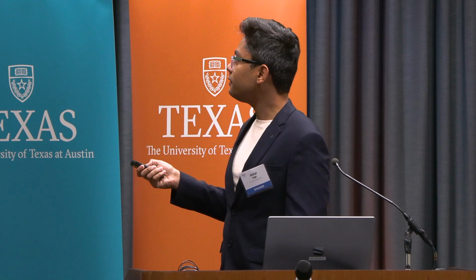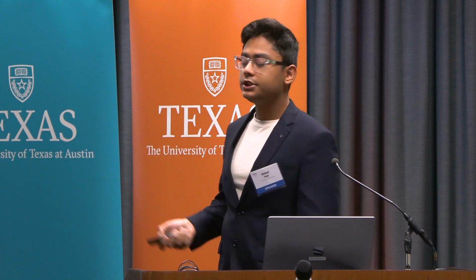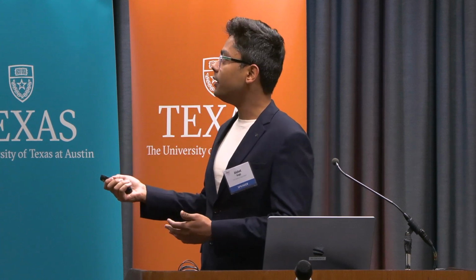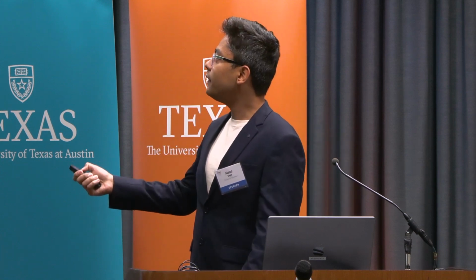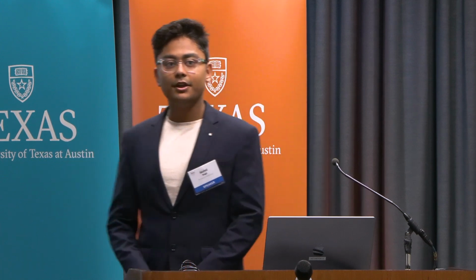So you can observe this phenomena with other metals and supports. One thing is that we want the support, which is TiO2 in our case, to be a reducible support. So it could be, let's say, niobium oxide, which is again reducible, but something like aluminum oxide cannot be used to observe this phenomena because it won't reduce even at high temperature. So that's one. And then you usually want the metal to be a high surface energy metal. So something like platinum, palladium, or even iridium can be used to see this phenomena. Cool. Thank you.